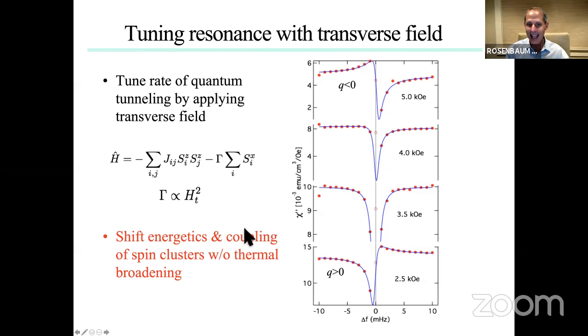So I'm shifting the energetics and the coupling of the spin clusters. The Fano parameter Q being 0 is interesting because that's where you basically decouple from your environment. That's what it means. There's no interference between those paths. There's no more response to the external field, okay? And you can see that happens around 3.5 kilogauss here.